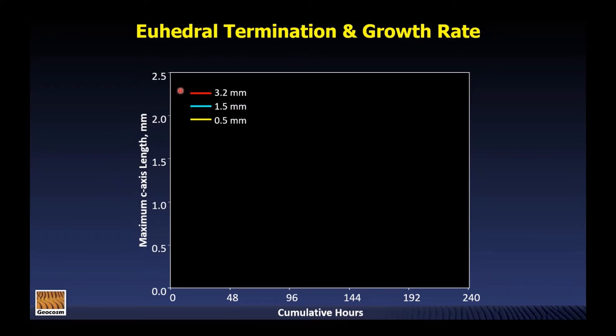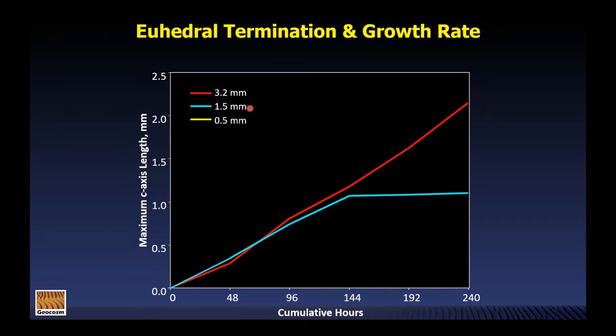So let's begin by looking at the growth history for this large crystal here. And you can see that over this period in the reactor, it grew at a linear rate. All right, now let's take a look at the growth history of the smaller crystal. Interestingly, it grew at the same rate as this larger crystal through 144 hours in the reactor. After this, though, we see a precipitous drop in the growth rate, about a factor of 20.